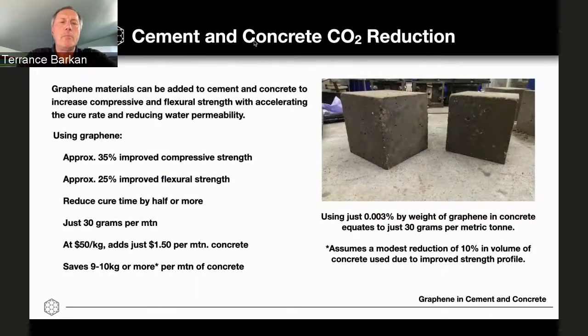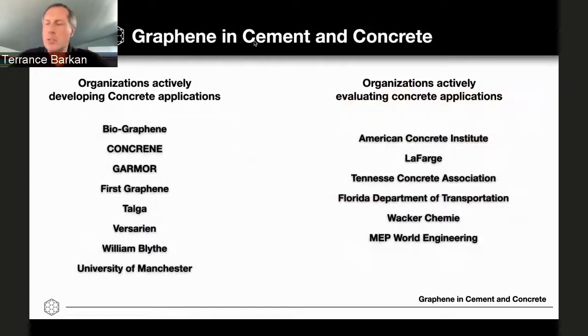Adding graphene to concrete improves compressive strength, flexural strength, and reduces the cure time, which is hugely valuable. And it can be as little as 30 grams of material per metric ton. And we now see graphene approaching price points at $50 a kilo or less, which means it's just $1.50 per metric ton of concrete. And yet, because you can reduce the cement composition in the concrete, you can remove somewhere between 9 to 10 kilos of carbon per metric ton. So the graphene not only strengthens it, but it allows you to have CO2 reduction, which is incredibly important as one of the top priorities globally, not just in the US.